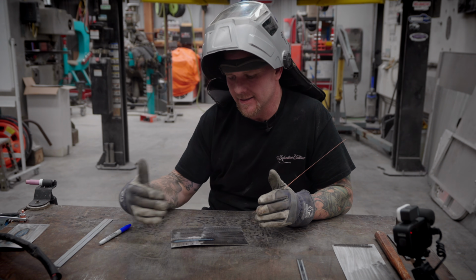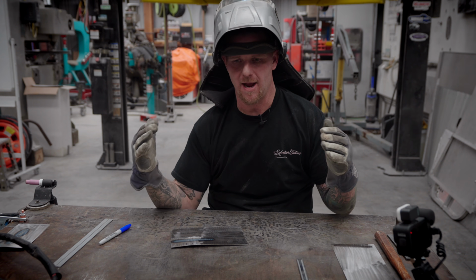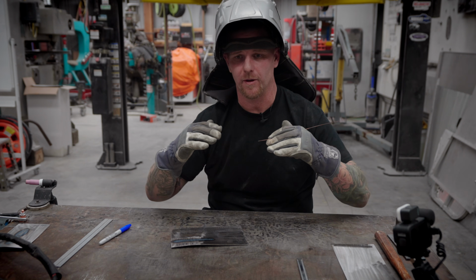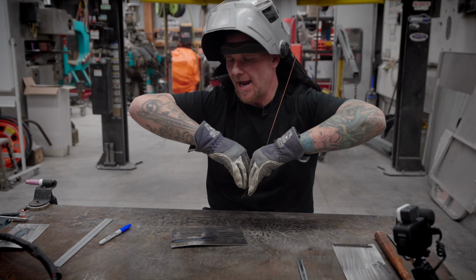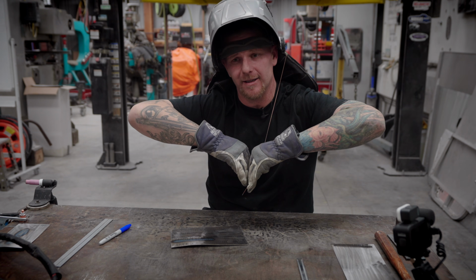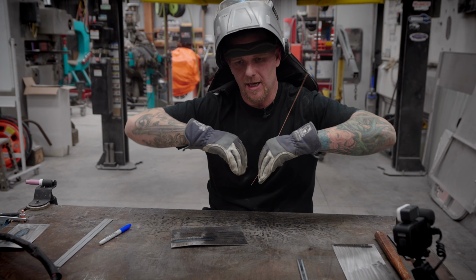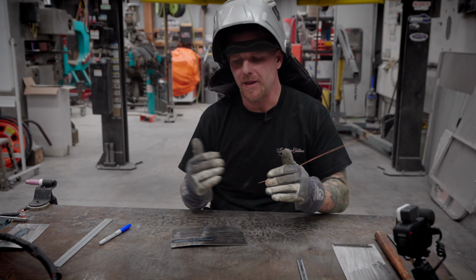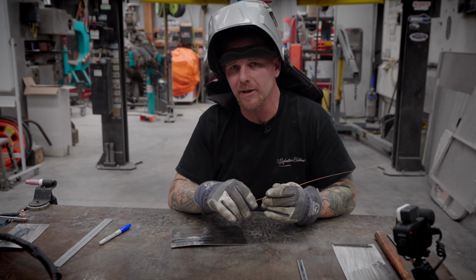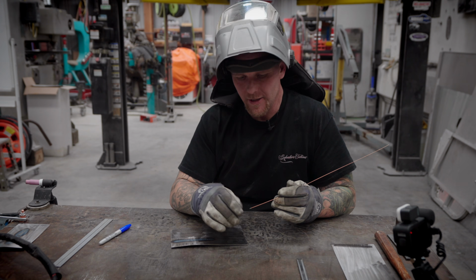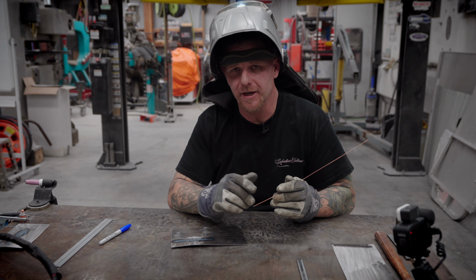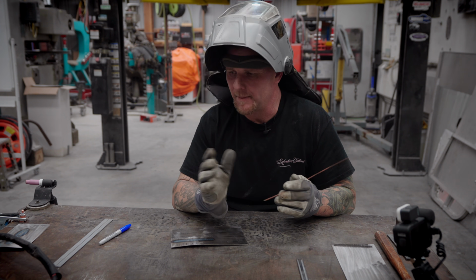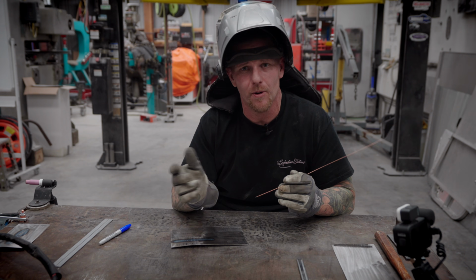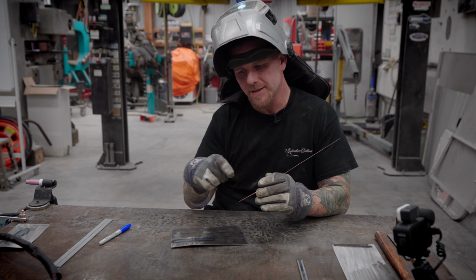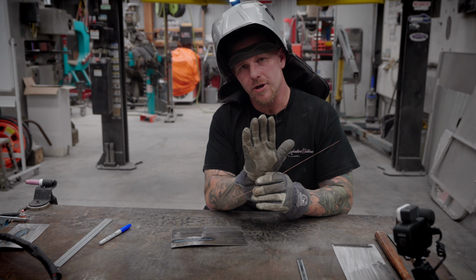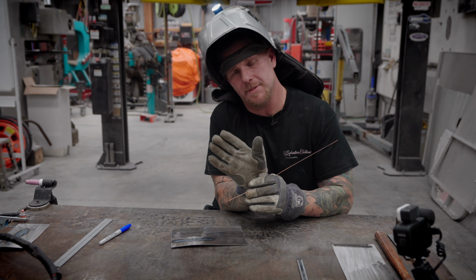And in doing this, you have to understand that when you have the force outside of the weld pool, if it's shrinking and pulling in, and out here in the V and the heat affected zone is slightly stretched, it's pushing down. And that's why we get that look as we TIG weld. You just don't see it as much with thicker steel, although it will move. I mean, if you're thinking about doing a chassis or a roll cage and you're putting a weld seam along a joint, know that it's going to pull that tube down.